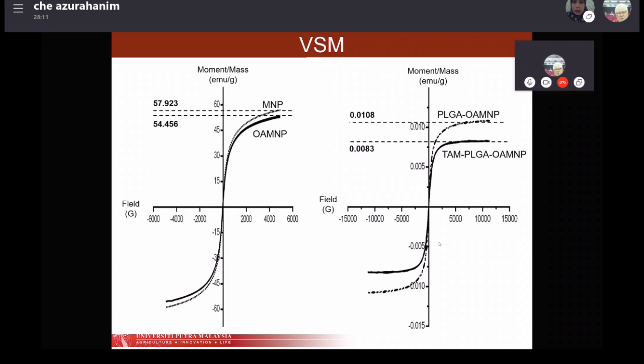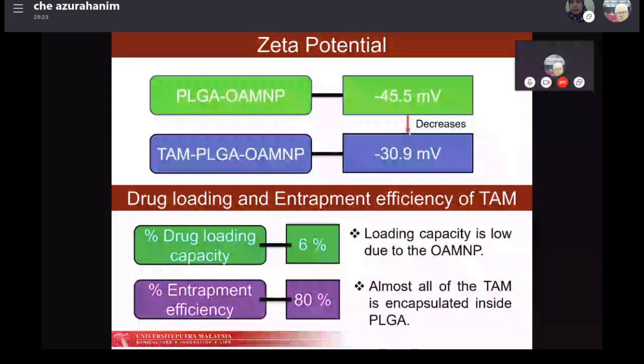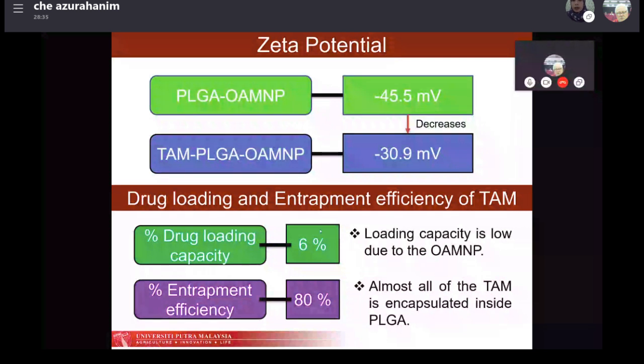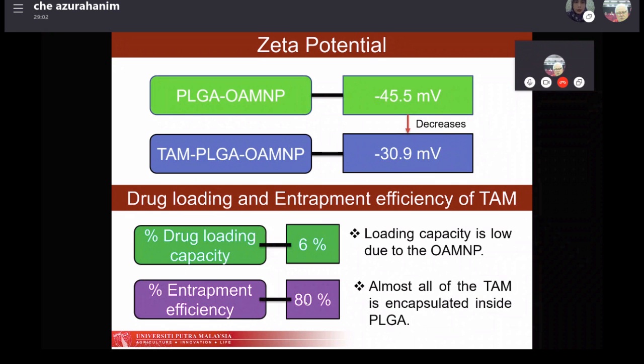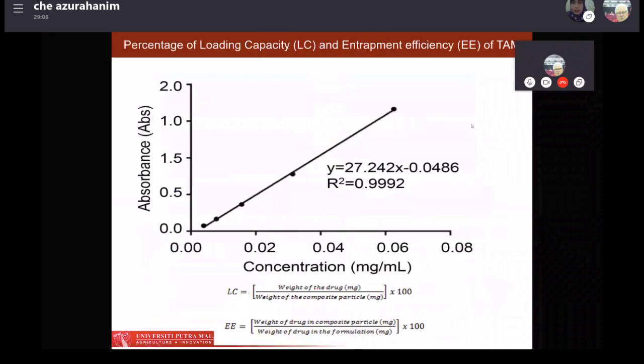Next, my student also tried doing zeta potential, and she found that after adding the anti-cancer drug to the PLGA on the MNP, the zeta potential decreases from minus 45.5 millivolts to minus 30.9 millivolts. In terms of the drug loading and entrapment efficiency of tamoxifen on the PLGA on the MNP, the drug loading capacity is only 6%. The loading capacity is quite low, maybe due to the oleic acid magnetic nanoparticle. In terms of the entrapment efficiency, almost all the drug is encapsulated inside the PLGA, where we found about 80% entrapment efficiency.